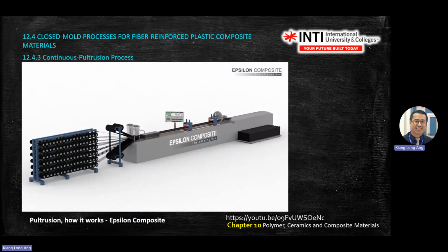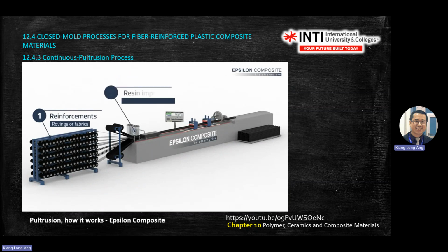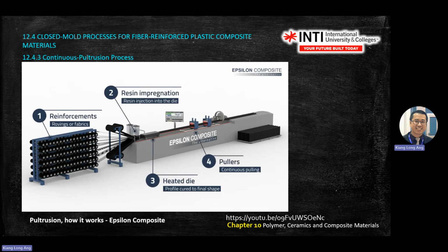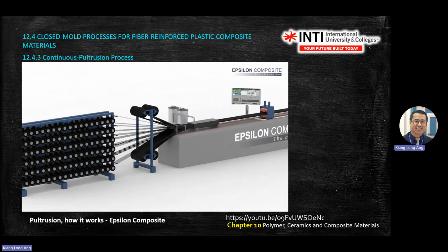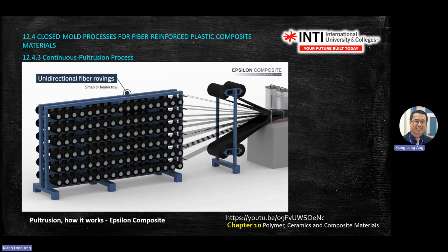On a pultrusion line, spools of fibers are impregnated with a resin, then formed and solidified at the shape required into a heated die. A pulling system allows the process to run continuously, and profiles are automatically cut at the desired length. The process can run 24/7 with very few human interventions, which guarantees an outstanding productivity and consistency matched by no other composite manufacturing process. Reinforcements can be used in the form of spools of unidirectional rovings and tows, textile fabrics with oriented fibers.